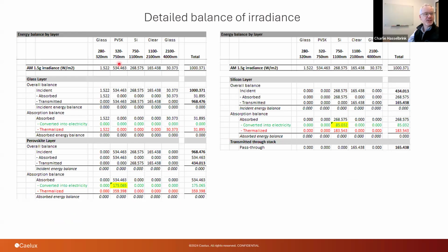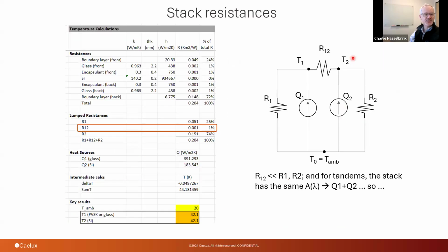And so you can go through, section by section at different wavelength bands, look at how much is converted to various things. And when you do this math, just on the resistor network, you'll quickly find that the resistance 1, 2, this one here, is a very small percent of the total resistance in the stack. The resistance on the front side is a little lower, because we've assumed that the resistance on the front surface of the glass is lower than the resistance on the back, just because it's also aided by natural convection. It's also got impinging air on it rather than being on the lee side of the panel and in a recirculation region behind the panel typically.